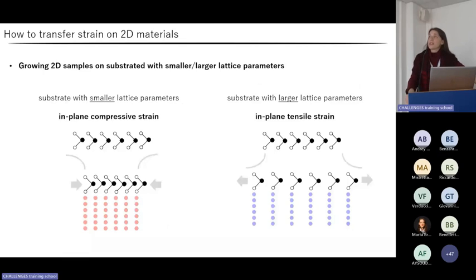Another interesting situation is that of two-dimensional samples synthesized by epitaxial growth techniques. In this case, the choice of the substrate itself plays a key role in determining the strain conditions of the overlayer. In particular, substrates with smaller lattice parameters compared with the sample favor the growth of films with a compressed lattice, while substrates with larger lattice parameters in general favor the growth of films with a stretched lattice. So in this case, we can say that the choice of the substrate determines an in-plane biaxial strain, which can be either compressive or tensile.